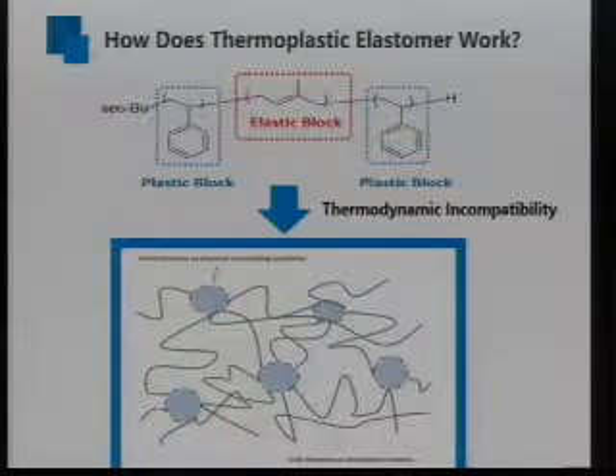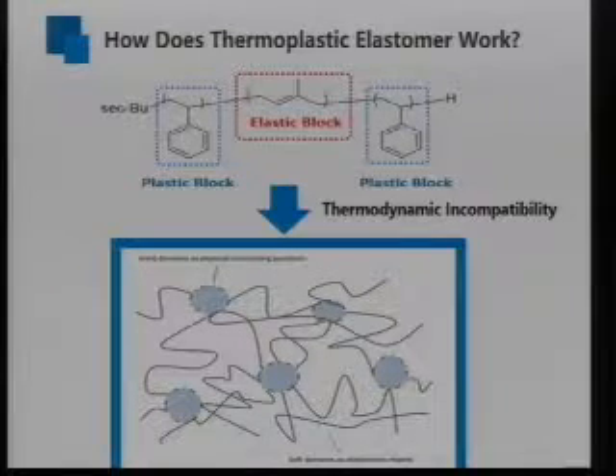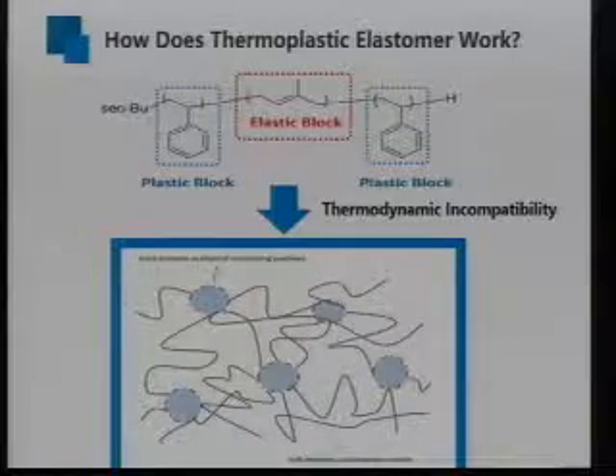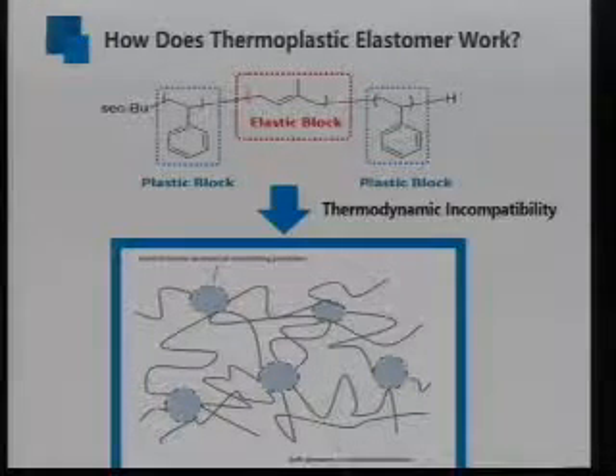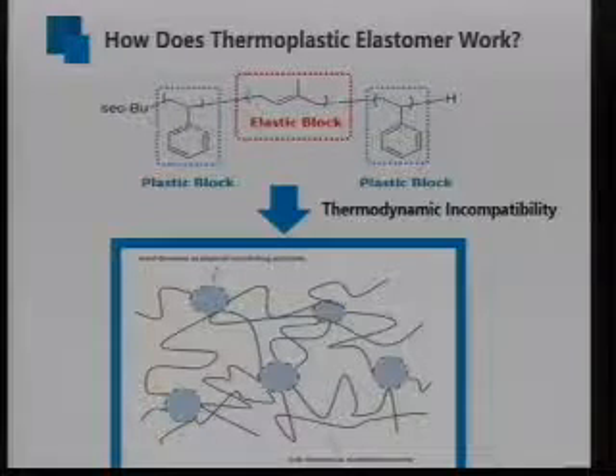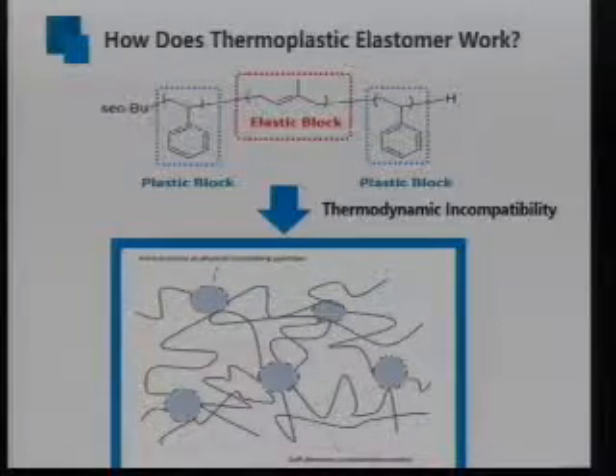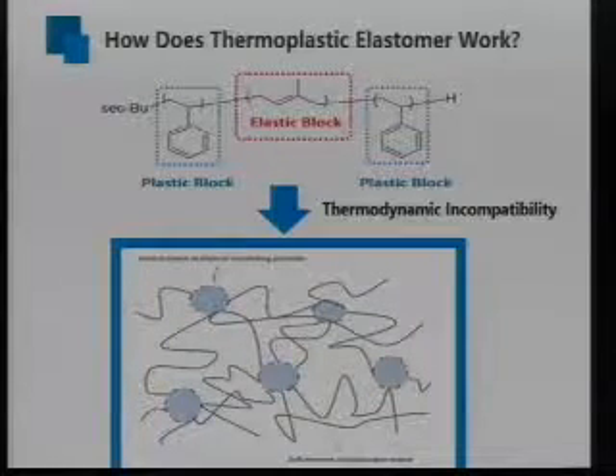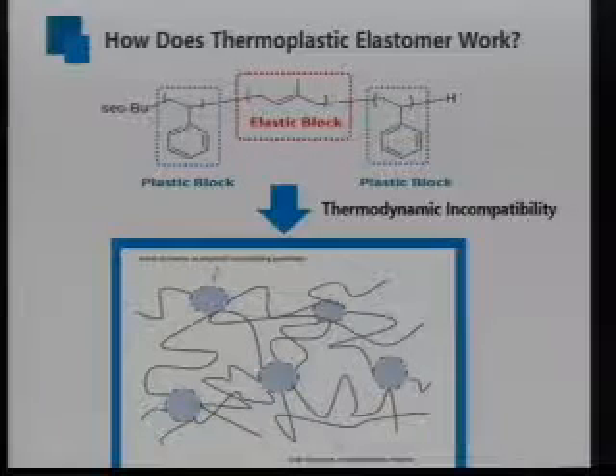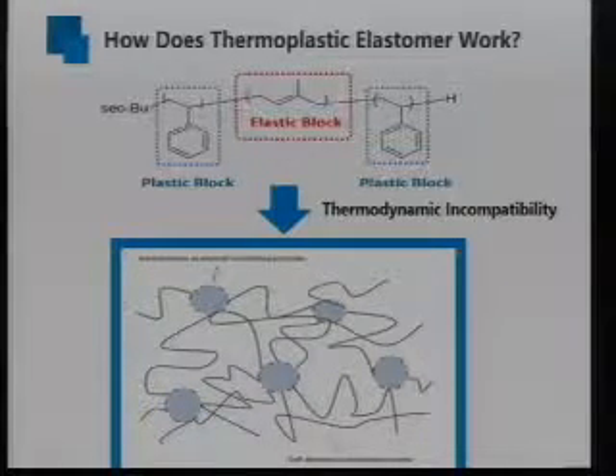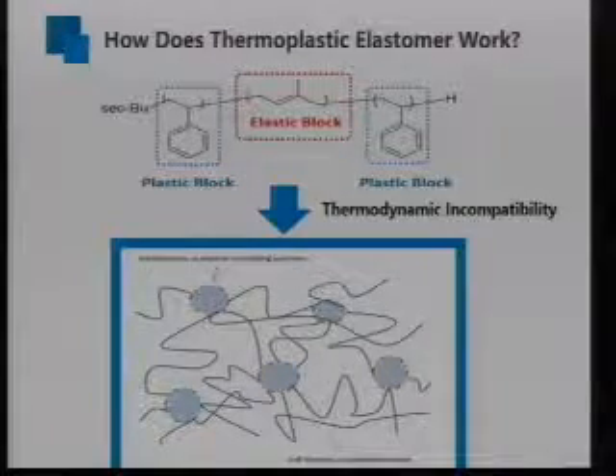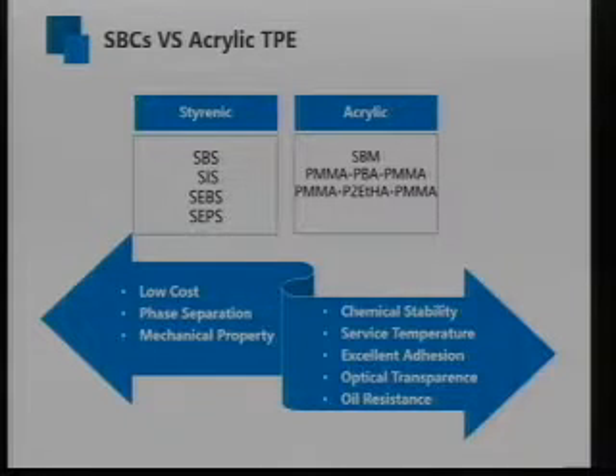Let's have a look at how thermoplastic elastomer works with the example of one of the most commonly used styrenic thermoplastic elastomers, this tri-block polymer of polystyrene, block polyisoprene, block polystyrene. The rigid block polystyrene can be used due to the thermodynamic incompatibility. The rigid block can be used to form the physical cross-linking junctions to provide the mechanical strength of the material. And the elastic block can form this kind of elastomeric matrix to provide the elongation property of the material. So this kind of styrenic thermoplastic elastomer has been widely used because of its low cost and good phase separation behavior and tunable mechanical property.